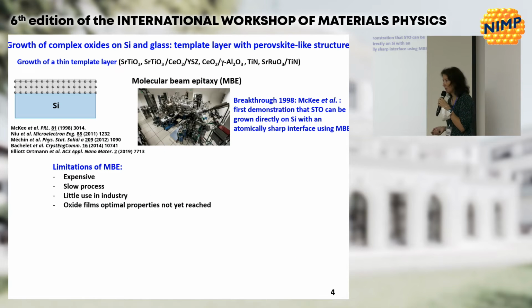So some attempts were made in the past to grow oxide on silicon, and the first breakthrough was made by McKee et al. in 1998. They have shown that it was possible to grow a very thin layer of strontium titanate on silicon by means of molecular beam epitaxy. And since then, a lot of other groups have presented other kinds of template layers, which are listed here.